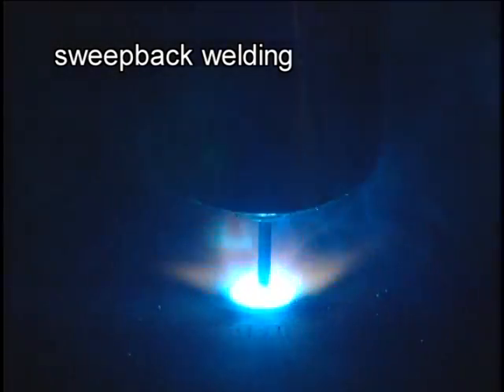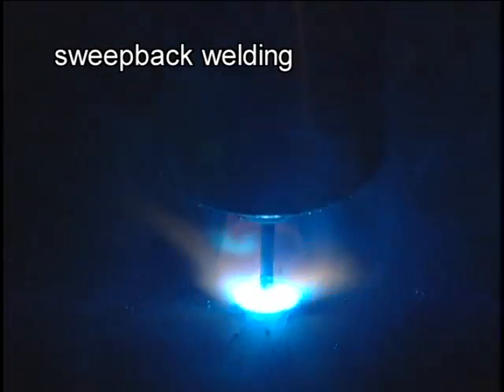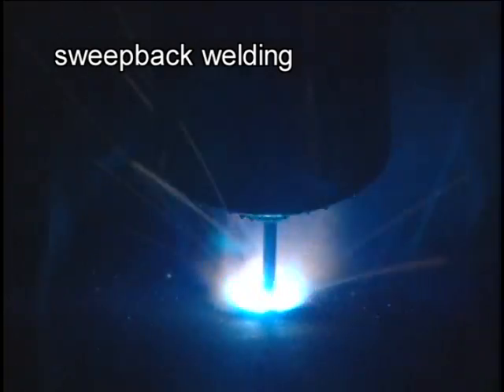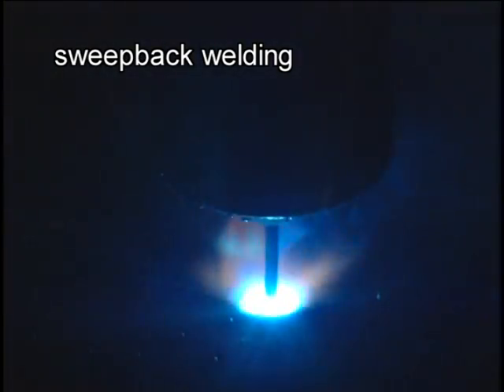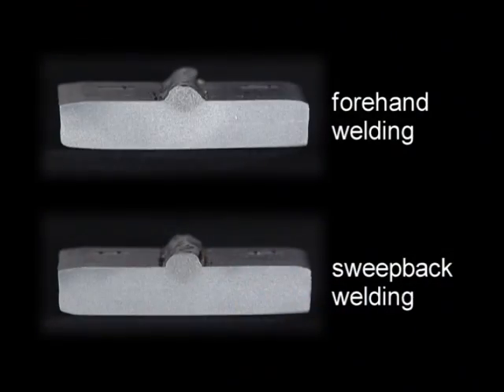The sweep-back welding method is used for special cases such as deep beveled welding that is able to handle this type of bead shape. Opposite characteristics are shown in the weld macro section when forehand welding method and sweep-back welding method are compared. Observe the differences in penetration, bead width, and weld reinforcement.